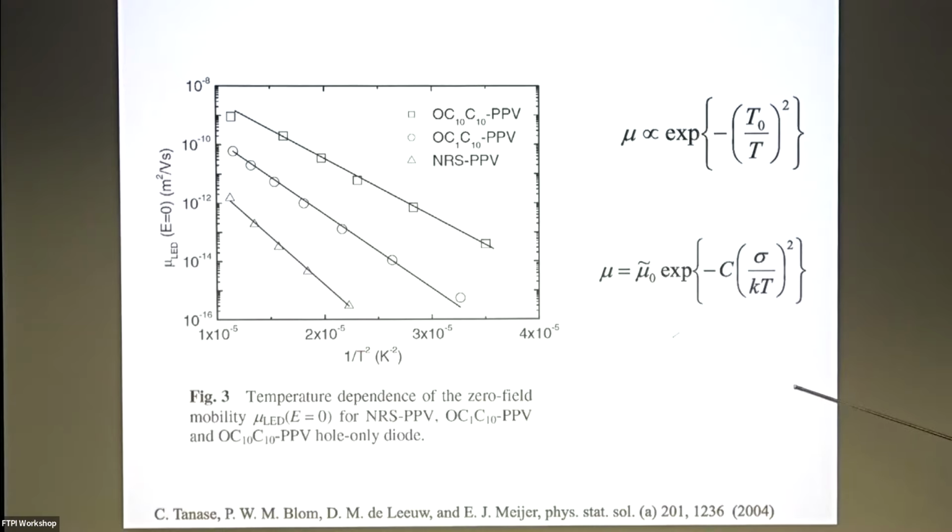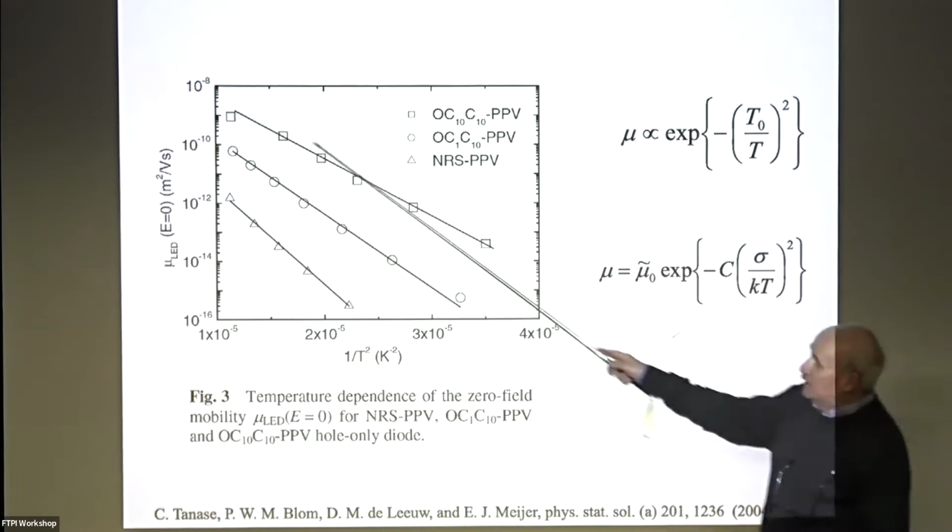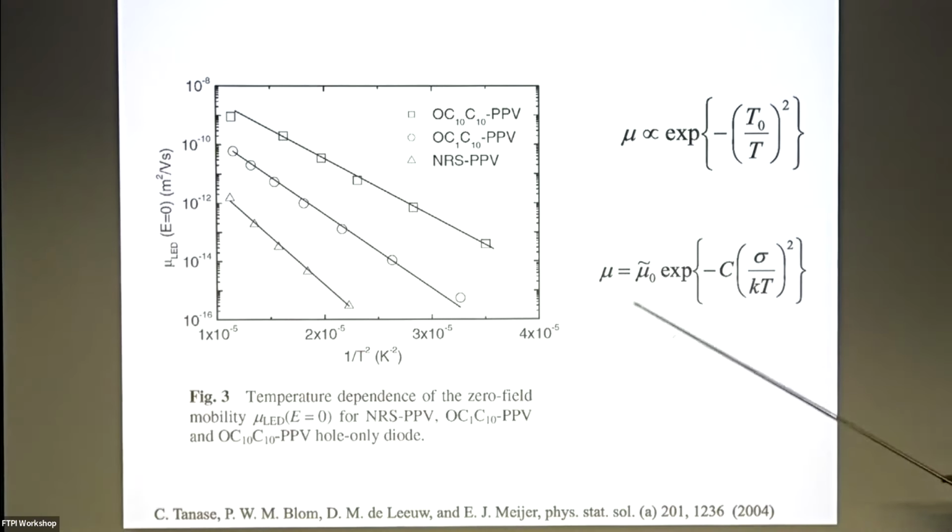And it's helpful because all experiments are measured in a diluted system, so not many electrons, with this peculiar temperature dependence in the exponent. We know C, we measure T naught, we determine sigma from this comparison. So that's why we do know the energy spread of localized states in organic materials, polymers, for instance.